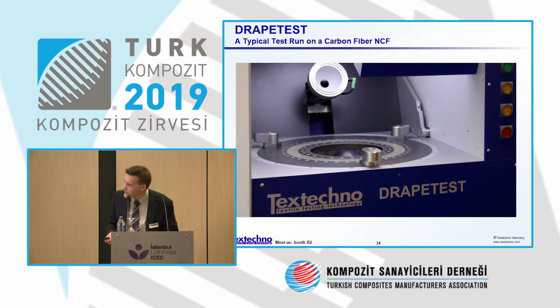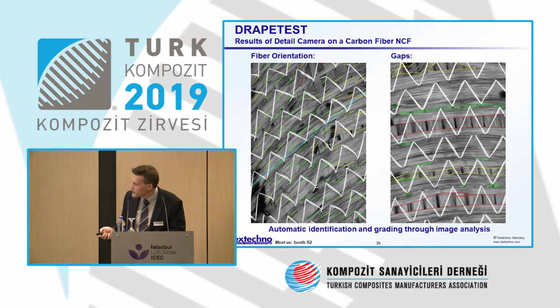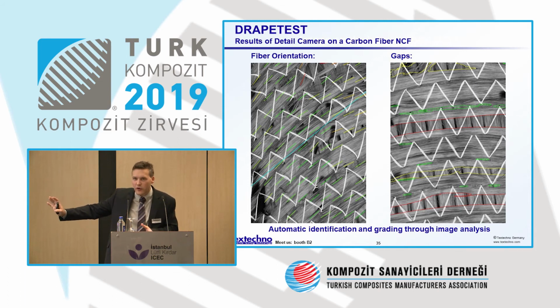So the movie apparently doesn't want to show, but basically it moves up, and at each drape height it makes a detailed picture, which in the end looks like this. And the software automatically goes in and checks for what the fiber orientation is and gives you, with a color scheme from green being okay, yellow being difficult, and red being catastrophic, an idea of how much the fiber orientation is varying due to the draping that you're doing. That's what you see on the left-hand side, and on the right-hand side you get an idea of how the gaps are forming, so also the automatic image analysis goes in and qualifies and quantifies how big the gaps are, and in the end you receive a statistical evaluation of these defects that you see.